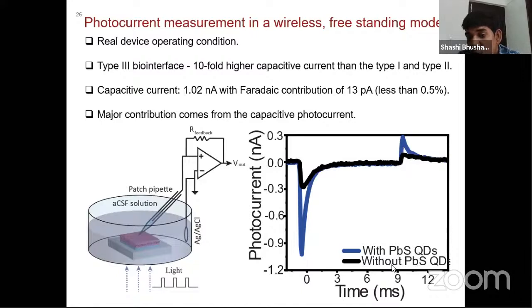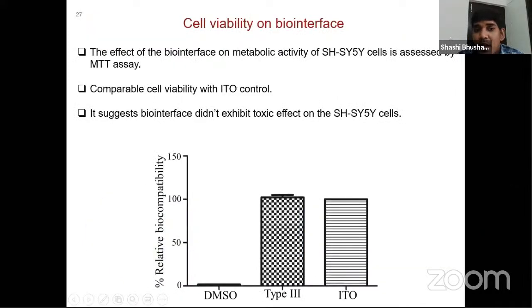Without PbS quantum dots, you can see that it is having only 0.3. So almost 3-4 times improvement in the device because of the mixture of PbS quantum dots with the polymer semiconductors. So this is showing our criteria, which we assumed is going to help us. It is helping us very nicely, with 3 to 4 times improvement. Further, what was the other criterion? That was the third criterion, that it should be biocompatible. So initially we started with SH-SY5Y. These are cancer model cells, neuron cells, available in the market and also made in the lab basically.